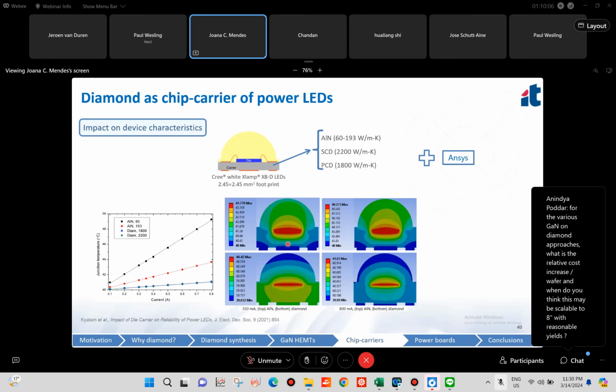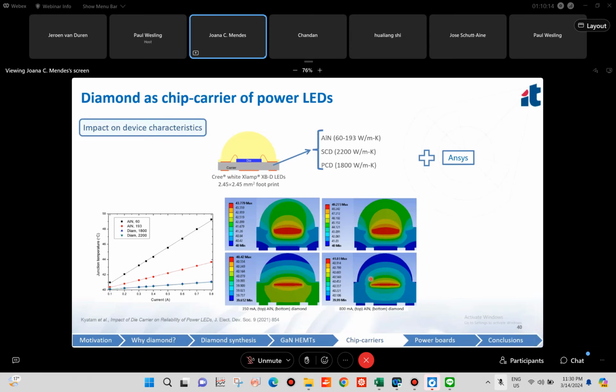And here on the left, we have a nominal current of 350 milliamps. Here at the right, we have 800 milliamps. And curiously, in these two extreme scenarios, the junction temperature using a diamond carrier at 800 milliamps is 41 degrees, which is lower than the junction temperature at 350 milliamps using an aluminum nitride carrier. And we can also see here, especially from here, that actually it doesn't make that much of a difference to use single crystal or polycrystalline diamond in this scenario.